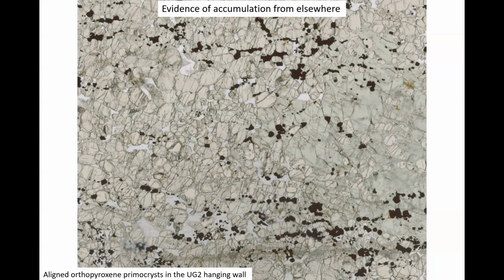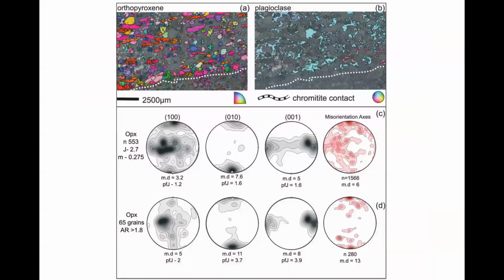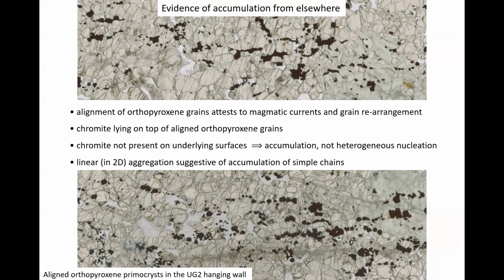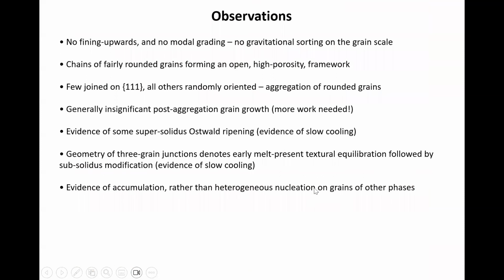I think we do have evidence of accumulation elsewhere in the hanging wall, in that the hanging wall is an orthopyroxenite. It's formed of elongated orthopyroxenes with interstitial clinopyroxene, and the orthopyroxene shows a lineation. So we've definitely got some sort of current migration and reorganization of our orthopyroxenes, for sure, just centimeters above the chromitite horizon. And what we also see is that the chromites form chains that lie on top of these current-sorted orthopyroxenes. And I would argue, and Zoja as well, that this means those chains were part of the depositional assemblage, if you like. They were there as part of the crystal accumulation. So that gives us evidence of accumulation rather than heterogeneous nucleation on grains of other phases.